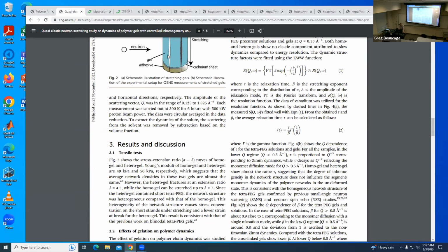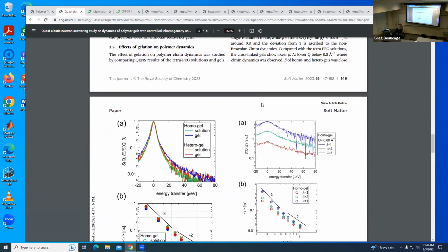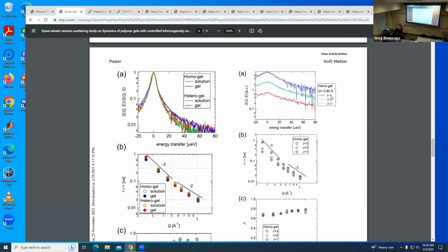The thing will relax, right? It's stress relaxation. It's gooey stretching. Eventually there'll be no stress on it at all, so it'll just be a mess, kind of. So anyway, that's what he does. He has different strains, 1, 2, 3. One's from this plot, and 2 and 3 are the two stretches he does. When lambda is 1, the strain is 0. Lambda minus 1 gives the strain, so it's actually a strain of 100% and 200%. And those are the curves.